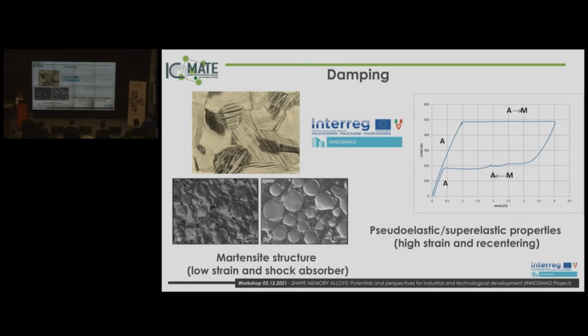The pseudoelastic properties are another way to damp the mechanical vibration, because in this case we consider high strain of deformation. By this particular curve, we have all this mechanical energy dissipated in mechanical hysteresis. And then we also have the recentering properties. The material deforms, accommodates the deformation, and then recovers its shape, recentering the structure where it is applied.